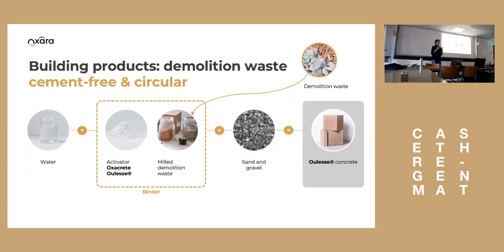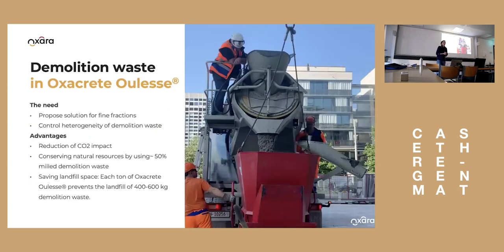So now I'm going to illustrate again how Oxara is using it. We are milling the demolition waste and combining it with some activator, and then we have the water and this binder of milled demolition waste, where the demolition waste accounts for up to 50% or around. Then we add sand and gravel and have a concrete-like material, but with a cement-free binder. We are following this strategy because we see the need to propose a solution also for the fine fractions of the recycled granulates, or rather, these particle sizes can vary a lot. And so by milling, one can at least control this heterogeneity. That is why we want to take the approach of using it in the milled form.